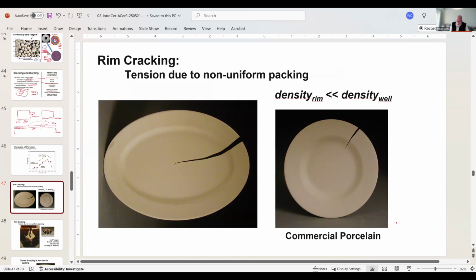In this case, I have a uniform gradient from outside to inside, greatest gradient, lowest density on the exterior, and to the center. Here, in the center here, okay, I end up with a uniform density here. So the crack only extends to the foot and then it stops. I could calculate my density gradient based on the crack opening displacement.